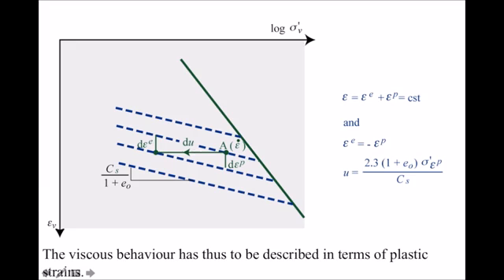But as the strain or void ratio is constant, in fact, the soil has to compensate with an equal value of elastic strain, which is shown here. And to have this, we have to decrease the effective stress. So we have the soil in what we call a relaxation test. The soil has to increase its pore pressure. So it's not a limitation, but it's a specification of the soil behavior.